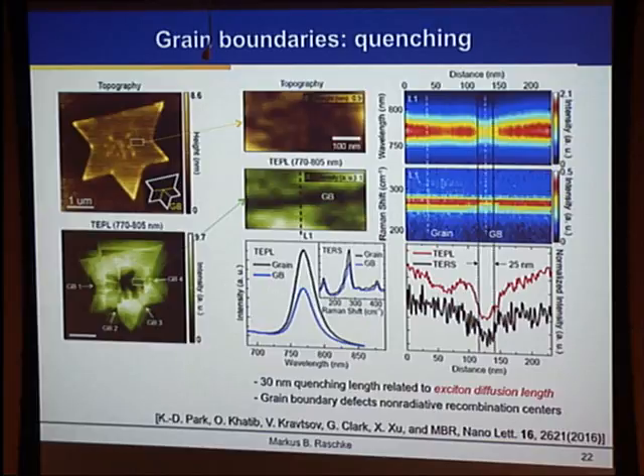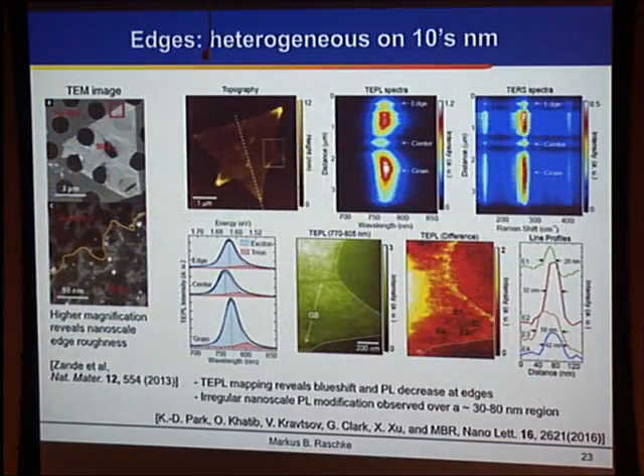We can then extend this study, and I will only show this very briefly. You can imagine we can study similarly the grain boundaries and the edges of the crystal. On the edges of the crystal, we see a lot more heterogeneity than at the grain boundaries. This has to do with the fact that the chemical stoichiometry of these crystals in the CVD growth is not as well defined. This work resolves a lot of questions about misinterpretation of signal changes at the edges. People thought these are due to topological edge states, and it's actually not the case, because there is incomplete stoichiometry because of the diffusion limited growth.